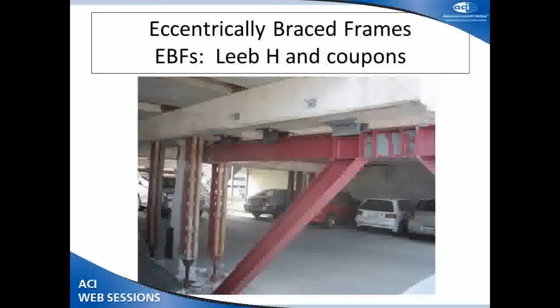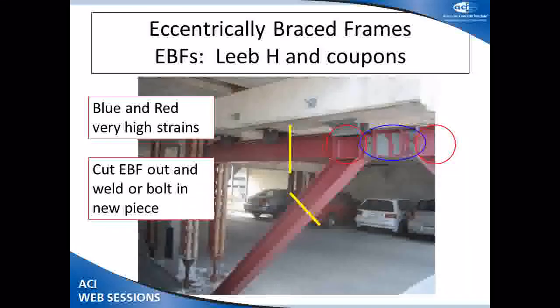Just so it's not a concrete problem alone. Structural steel. Here is an eccentrically braced frame, an EBF, in a parking structure of the hospital. You'll notice paint's flaked off. This is also what happened. The problem is that this weld here should have been there. If these were closer together, they should have been welding that surface to that surface. They took a shortcut. That bend caused a fracture in the flange. The flange tore and ran through the link. It's the same shot again.